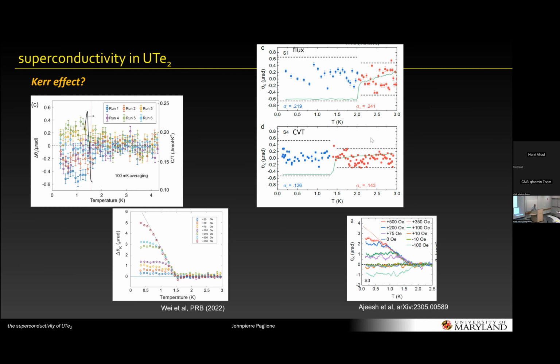So the Los Alamos group claims to have measured the same type of sample, but also the higher TC sample. So they don't see Kerr effect in any of them. And isn't there some conversation about some samples show one transition, some show two transitions? So there's sort of a correlation with Kerr effect and not, it has to do with that? So this is the data available, and so the statement is that Aaron sees Kerr effect in the samples he studied so far, which are the two. Which had two transitions. TC, yeah. And this, we don't know if it's two or one transition. No, that one is one. This is one, yeah, that's right. So Los Alamos has been claiming that the two TCs are due to some sample inhomogeneity. But it's not conclusive.